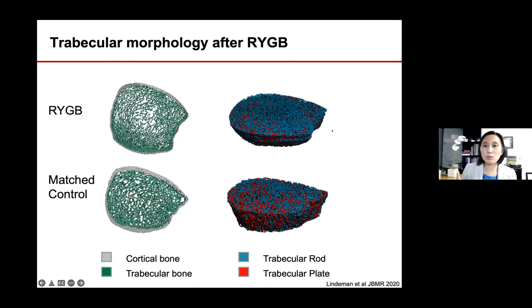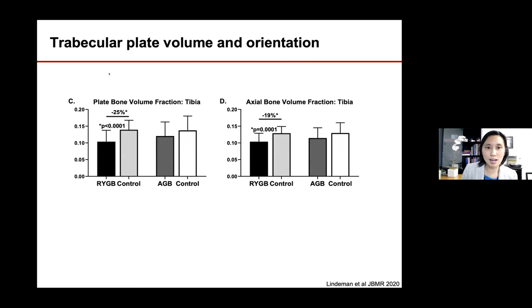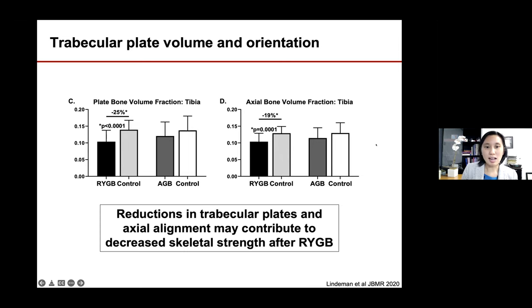So not only are you having a deterioration of trabecular architecture, you're actually preferentially losing the specific morphology of trabecular plates that provides the greater strength. And this just provides a quantification numerically of the plate bone volume fraction being 25% lower in the gastric bypass patients as compared to matched controls. And also here, you can see that there's a reduction in the proportion of trabeculae which are axially aligned in the gastric bypass patients as compared to controls. And both of these morphologic changes likely contribute to the decreased skeletal strength that is observed after gastric bypass.